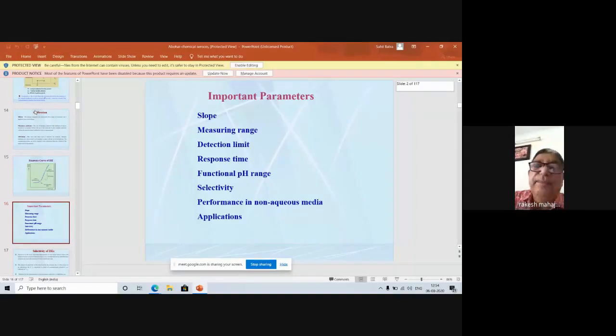The response time, when I say response time, what is the response time? Response time is the time taken by the membrane to give a stable reading, stable potential. That response time should be very small. If the response time is say 2 minutes, 3 minutes or 6 minutes for getting a stable reading, then that membrane is not good. Membrane is good only when you get a stable reading within 20 seconds or 30 seconds or 60 seconds, something like that, within 1 minute.